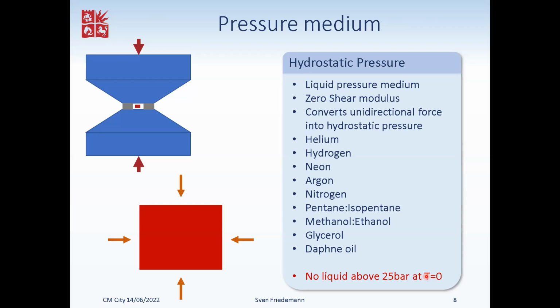So we want liquids, and here are pressure media listed in order of descending quality. Helium and hydrogen are the best pressure media, then neon, argon, nitrogen, so all noble gases and gases, then materials that are already liquid at ambient conditions, but have been mixed in order to avoid crystallization and hence suppress solidification of these materials. But none of these, including helium, are liquid above 25 bar when it comes to low temperatures.